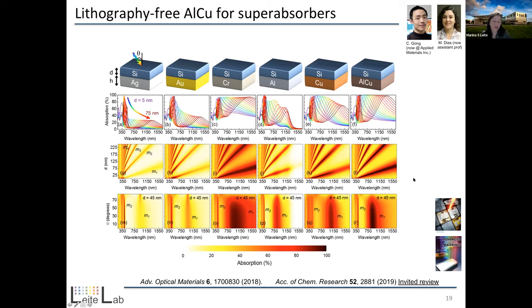So we experimentally demonstrated that these simulations do make a lot of sense. For the experiments, we obtained maximum absorption of 80%. So I think there is definitely room to optimize these structures once we fabricated them.